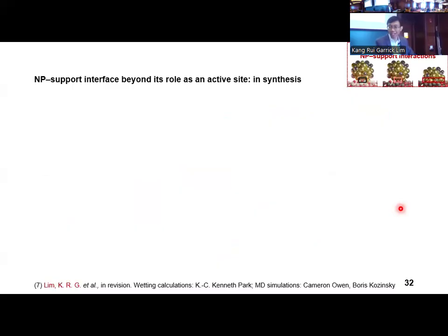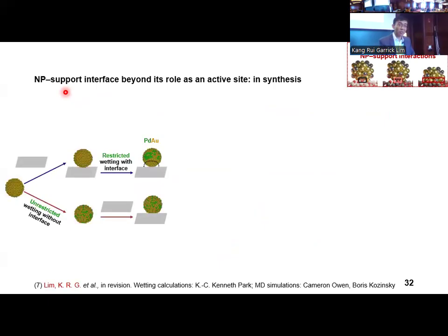Before I summarize this second half of my work, I want to highlight that the nanoparticle support interface can serve more than its typical role as an active site. In this other work, we show how the physical presence of the nanoparticle support interface directs secondary metal overgrowth and tunes the size of metallic ensembles on the nanoparticle surface. In this other work, we compare the palladium metal overgrowth step on supported gold nanoparticles or on unsupported gold nanoparticles before their immobilization under the support.